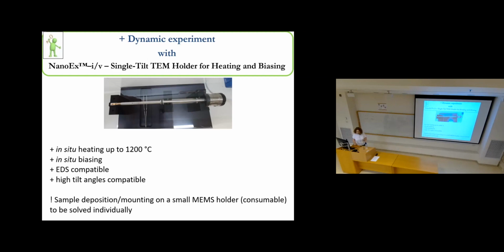But it's doable. It's not a problem with the colloidal dispersions for sure, because this is only a drop casting. But if we are talking about the focused ion beam lamella and other solid samples, there is a way to do that, but we need to solve for each specific sample. But it's doable, and the heating rates are enormous, from very, very slow, like 100th degree in second to 100 degrees in second. So it's quite flexible, but we are starting.